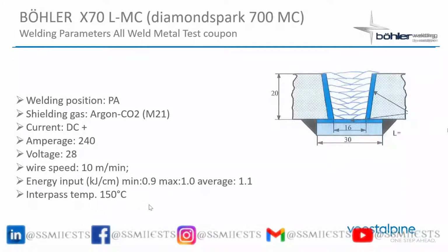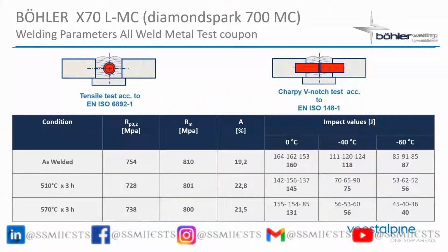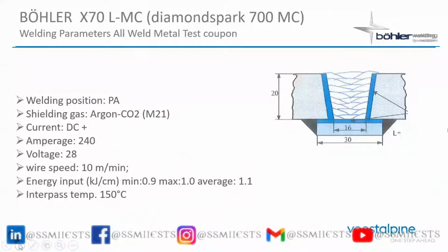Yeah, so this is a particularly high-strength steel welding wire called Diamond Spark 700 MC. These are the welding parameters that we've used. Basically, it was a mixed gas argon CO2 mixture in downhand position. So this is on a 20 millimeter thickness plate.